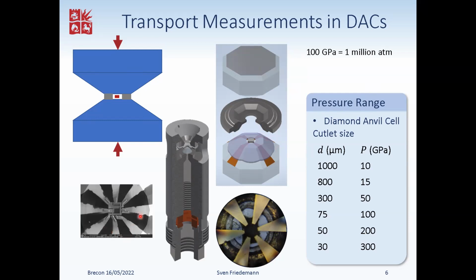The high pressure cells lend themselves to miniature microprobes in combination with FIB. So here is a picture of a sample that has been FIB cut and contacted directly on an anvil to electrodes that have been evaporated on there. So there are some good experiments one can do this way. It does, of course, multiply the success rate of FIB and high pressure, so one has to keep that a bit in mind when doing such experiments. But one can engineer some nice things here.